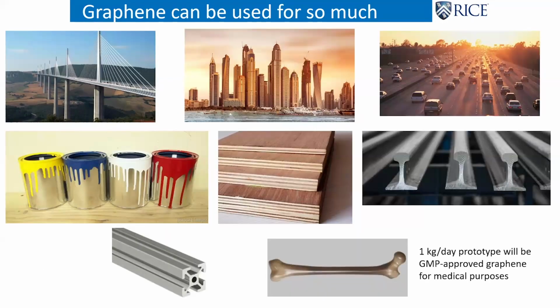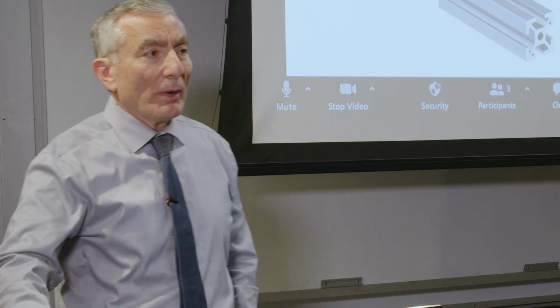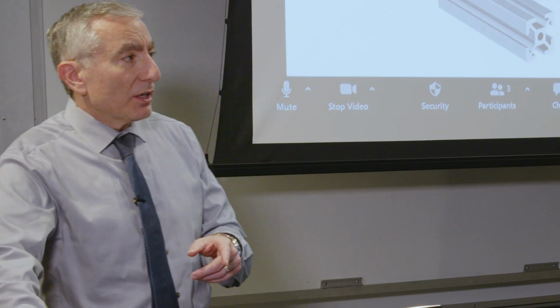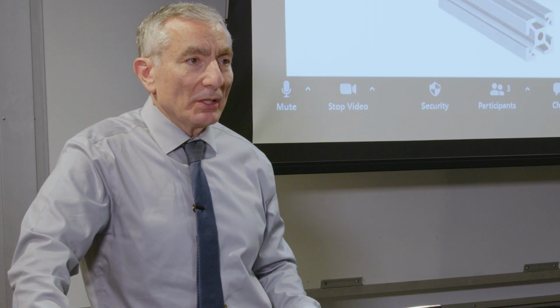So graphene can be used for so much. It's going into concrete. They've already got an asphalt product. It can triple the life of an asphalt road. Think about that: tripling the life of an asphalt road, how much energy that would save. It also brings up the working range of asphalt by about 11 degrees centigrade. We don't use as much asphalt around here; we normally use concrete because it gets so hot. If you can bring this up 11 degrees centigrade, which is a lot more degrees in Fahrenheit, that's a big change without affecting the lower temperature working ability. So it makes asphalt more available to be used instead of concrete.